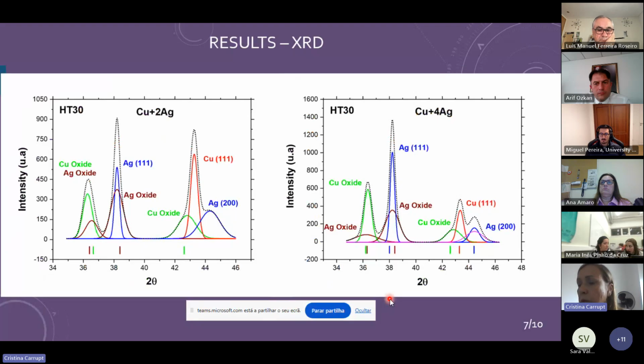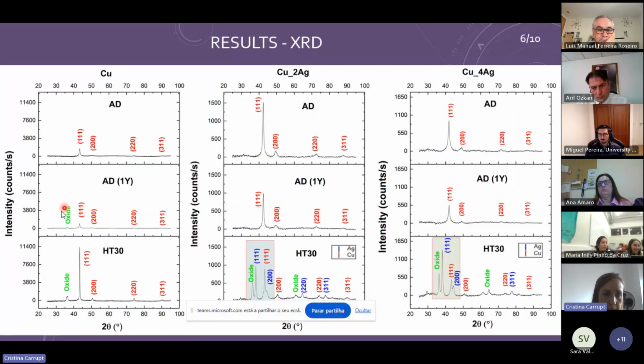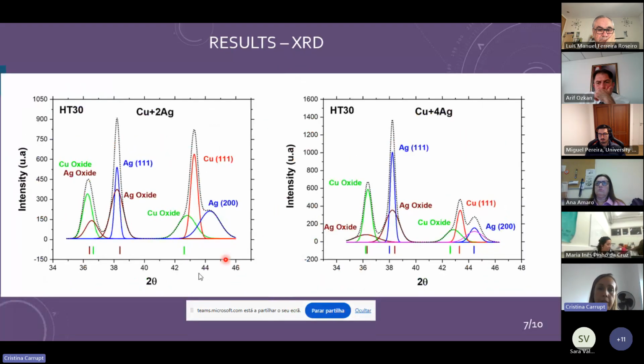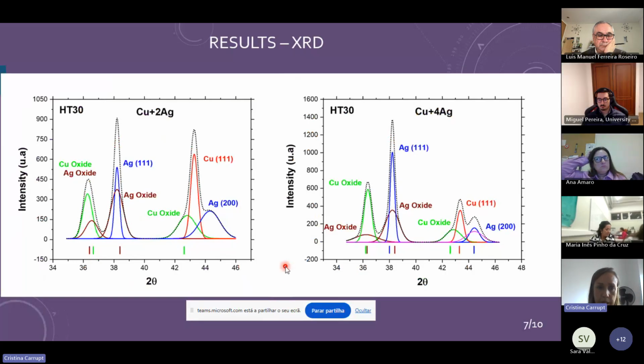The heat treatment promotes an oxidation of the films, and here we can see a little peak of oxide, but not in the other. But after heat treatment, the peaks are clear. Here we can see with more detail the peaks of oxides.